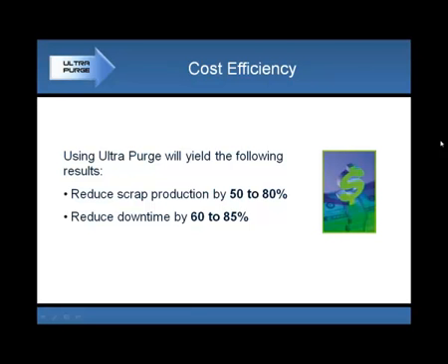Now, using UltraPurge has proven an efficiency in reduction of scrap, actually, between 50 to 80%, and 60 to 85% in reduction of downtime. Now, these numbers are very far apart, 50 to 80, 60 to 85, because, again, that depends on many different factors. Again, as we said before, this is a system approach. This is not a miraculous solution.